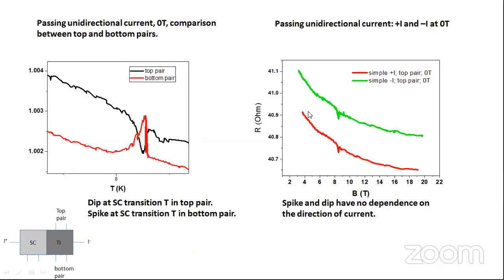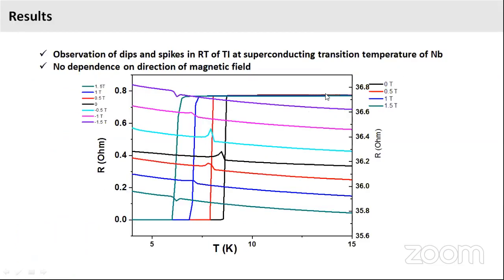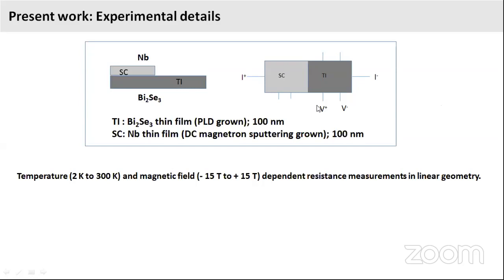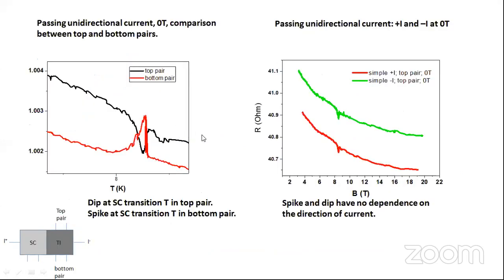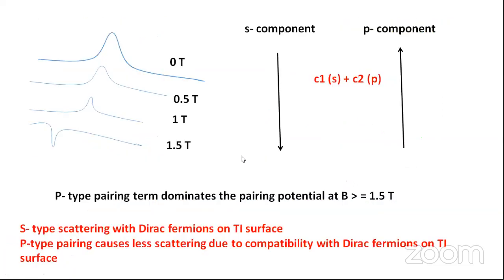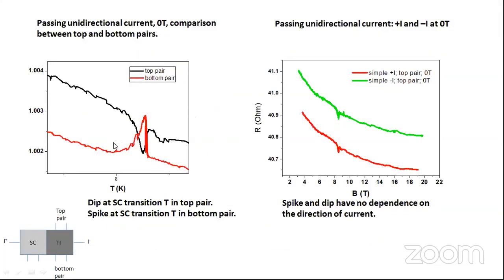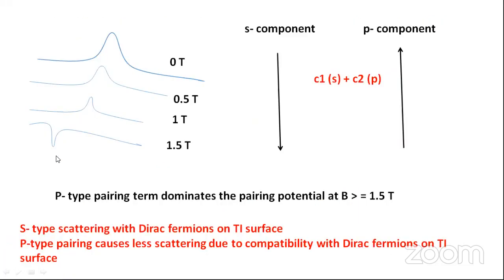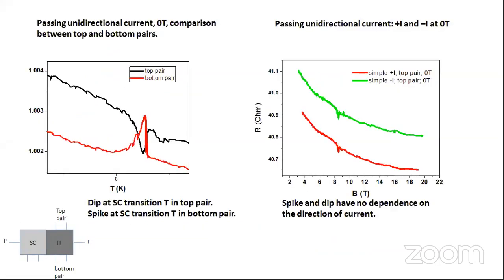All these measurements were done on the bottom pair of leads over here. And we wouldn't generally expect there to be any variation between the bottom pair of leads and the top pair of leads. But what we observed is that when we accidentally measured on the top pair of leads, there is the exact opposite phenomenon. There is a dip at zero field in the top pair, unlike in the bottom pair where it's a spike. And as the magnetic field strength increases, just as there was a spike to dip flipping in the bottom pair, there is a dip to spike flipping in the top pair. So it's the exact opposite of what happens in the bottom pair.